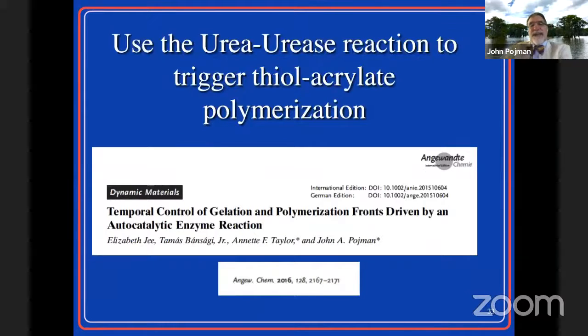Well, then we realized, if we take this pH change, can we use it to trigger or cause another process to happen? The answer is yes. We use a thiol-acrylate polymerization. So a thiol is a weak acid, and if we can deprotonate it, it can undergo a Michael addition with an acrylate.